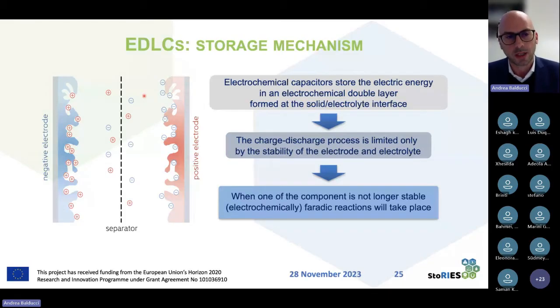Typically, among the two of them, the electrolyte is the one that is the most unstable. So typically, the potential in which this storage process is possible is given by the electrochemical stability of the electrolyte. In water, for example, this is more or less 1 volt. If you go to an organic electrolyte, you can reach 3 volts. And this is the reason why in commercial systems, we have systems working between 2.7 and 3 volts.